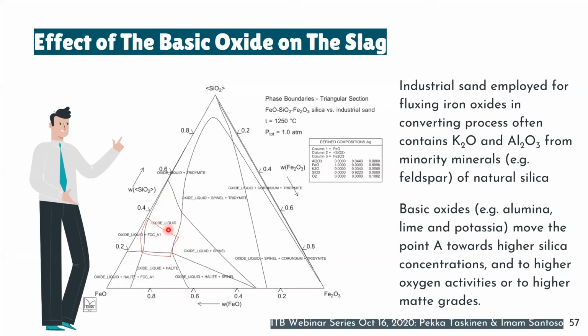You can see here, and also the point A where the slag and silica and magnetite is saturated, it moves upwards, or in other words, the slag area becomes wider. So this is more or less the effect of the potassium and alumina on the chemistry of the slag.